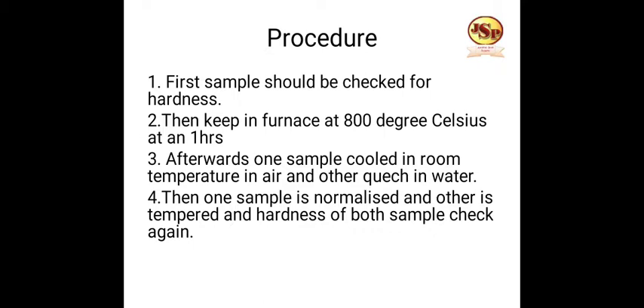The procedure of the experiment. First, the sample should be checked for hardness and then kept in the furnace at 800 degrees Celsius for 1 hour. After that, one sample is cooled at room temperature in air and the other is quenched in water. Then one sample is normalized and the other is tempered, and the hardness of both samples should be checked again.